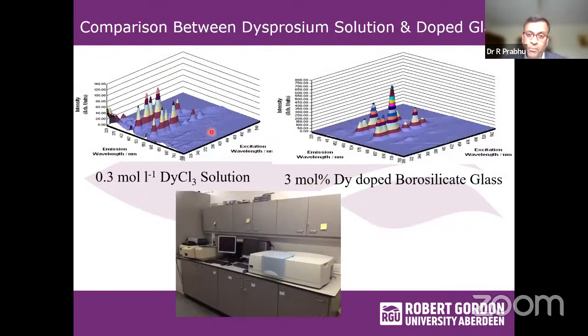The first thing is to compare the emission spectra from a typical rare earth called dysprosium. So we tried to see what the effect is in solution and what the effect is of the same ion in borosilicate glass. You can see this is a spectral emission in a 3D view. This is the excitation and this is the emission. And you can see in the liquid, you have sharper emissions than in the borosilicate glass. And these absorption bands have broadened, while here in the liquid, they're much sharper. Again, the absorption band in glass is higher than in the liquid.